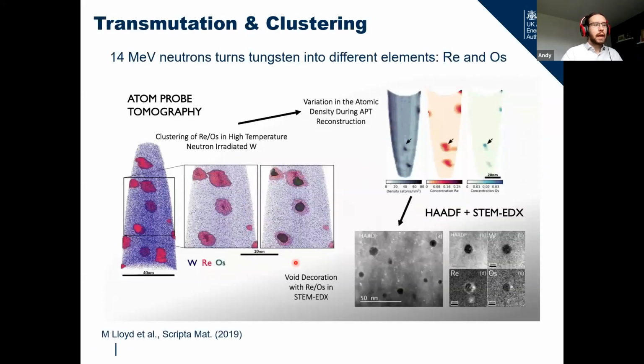But what can happen is the secondary effect that I said about absorbing the damage, as well as absorbing the neutron damage in our material. In this case you can see in these pictures here, these dark areas are actually holes. So these are those cavities or bubbles that I mentioned previously. We can actually use a very specialist microscope called an atom probe, which can map the chemical compositions, the ionic, the isotopic identities of the atoms in 3 dimensions on the nanoscale.